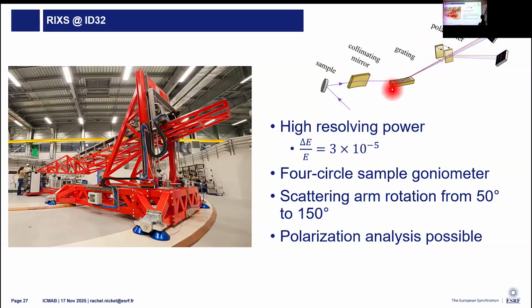So instead of having the grating straight through to the detector, we include a polarimeter where we reflect and can do polarization analysis. This is useful if there's particular excitations, be it a magnon or a phonon, where you want to excite in horizontal and vertical polarization and see the difference. It can help discriminate where the peaks are coming from.